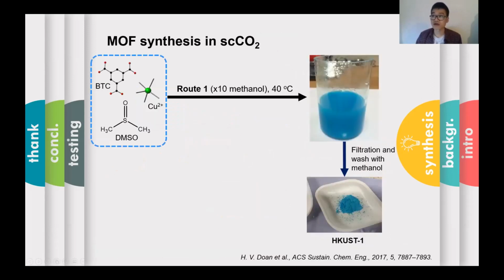In most of the conventional MOF synthesis, for example, the hydrothermal synthesis of HKUST-1, copper nitrate and trimesic acid are mixed in DMSO to make a stock solution. After that, a copious amount of methanol needs to be added, heated at 40 degrees C, and left for a few days. After that, the solid MOF will be filtered and rapidly washed with methanol to remove the solvent in the pores.